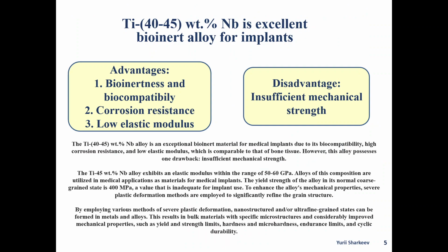The titanium niobium alloy is an exceptional bioinert material for medical implants due to its biocompatibility, high corrosion resistance, and low elastic modulus, which is comparable to that of bone tissue. However, this alloy possesses one drawback: insufficient mechanical strength. The titanium niobium alloy exhibits an elastic modulus within the range of 50 to 60 gigapascals. Alloys of this composition are utilized in medical application as materials for medical implants. The yield strength of the alloy in its normal coarse grained state is 400 megapascals, a value that is inadequate